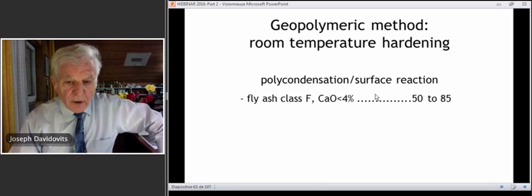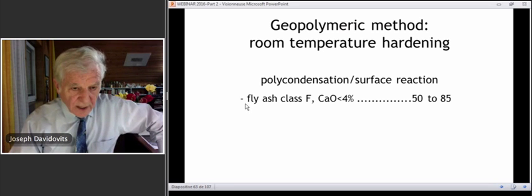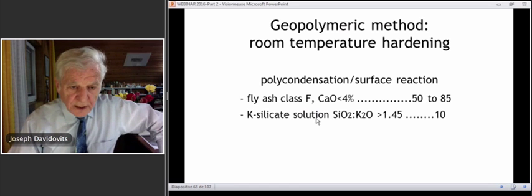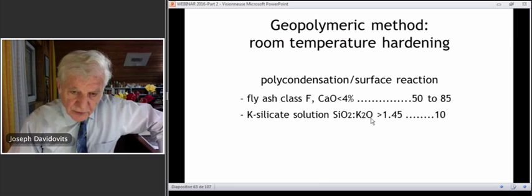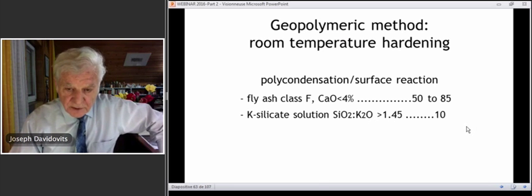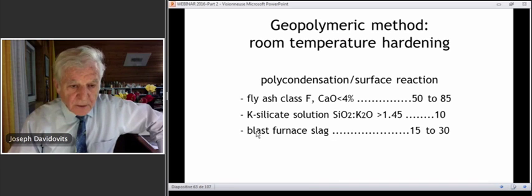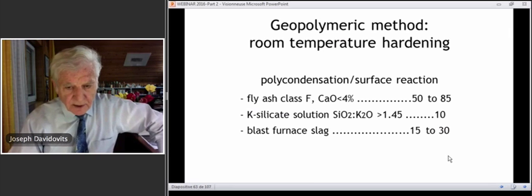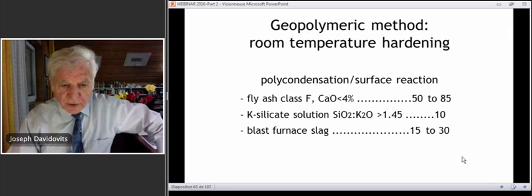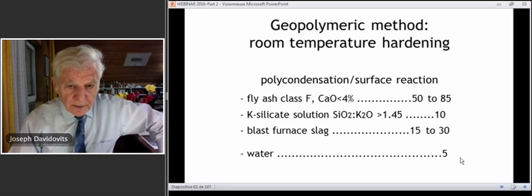And we make our matrix with the fly ash. We take fly ash between 50 and 85%. This is a lot. We have our potassium silicate solution. You can take potassium silicate solution with a ratio higher than 1.45. This is very mild. We add the blast furnace slag depending on the ratio and the blast furnace slag you have. This is the knowledge that you have to acquire. And then the water. And this is what you get.